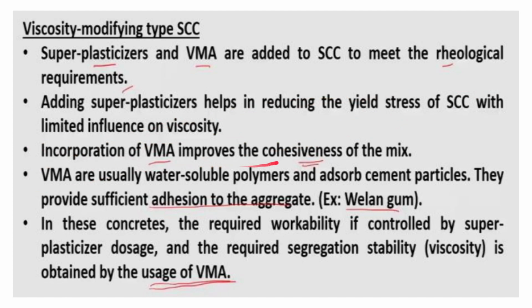The incorporation of VMA improves the cohesiveness of the mix, because it will be more viscous. VMAs are usually water soluble polymers and they adsorb cement particles. Because of their viscous and cohesive nature, they provide sufficient adhesion to the aggregate. One of the industrially used VMAs is Welan gum, so we can use that as a VMA.